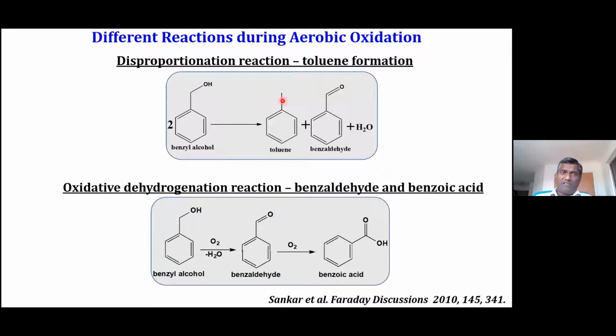Now, we found that the origin of toluene is a disproportionation reaction, very similar to the Cannizzaro reaction. So 2 moles of benzyl alcohol disproportionate to give toluene and benzaldehyde in an equimolar mixture. This reaction is responsible for the production of toluene, whereas oxidative dehydrogenation of benzyl alcohol results in benzaldehyde, which oxidizes to form benzoic acid. So there are two parallel reactions that happen in this flask, for example.